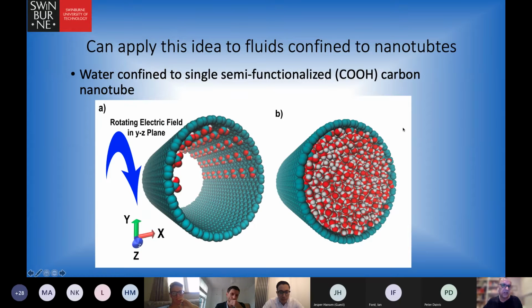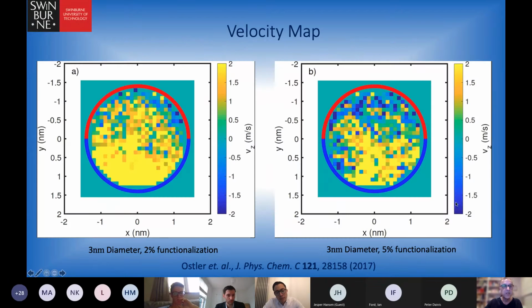Now, very, very quickly, I'll go through and show you that you can do the same with nanotubes. So you don't have to do it with just planar surfaces. If we now functionalize a carbon nanotube, semi-functionalizing half of it with carboxyl groups to make it more hydrophilic, while the other half remains carbon nanotube, fill it with water, and apply a rotating electric field, we can see that we get this kind of velocity map.